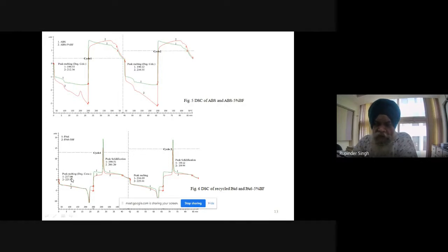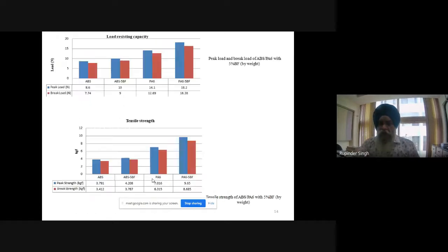Similarly, the trend was observed for another substrate, that was polyamide, and polyamide reinforced with banana fiber. So you can see earlier with the virgin material, single material, it was 217. Now it is 225. So a similar trend was observed in the second cycle. We are interested to see in repetitive cycles whether the thermal stability is there, and if it is absorbing a similar range of energy in the heating cycle, and almost similar is being released in the cooling cycle, we consider that this is a thermally stable material.